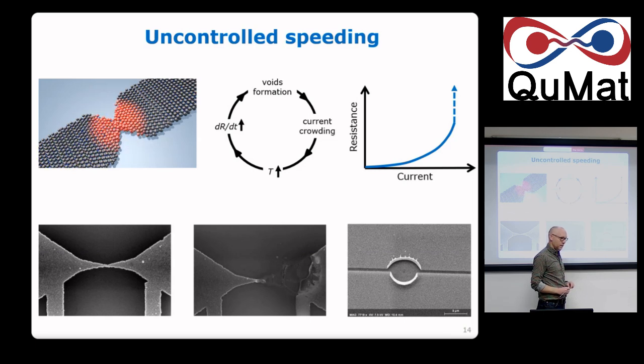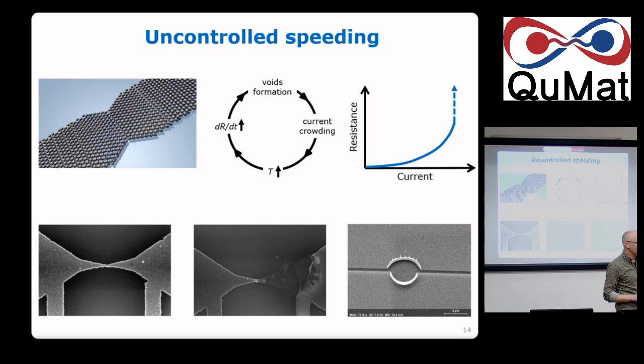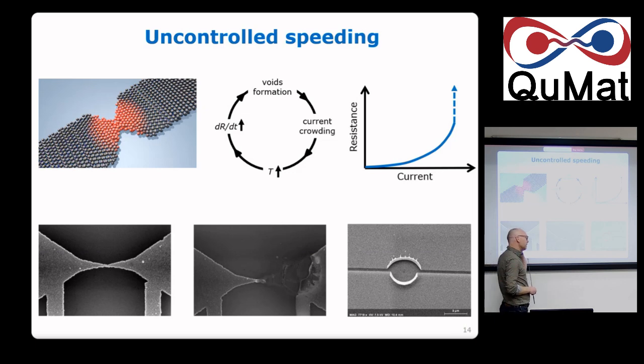Your initial slides had some comparison to the melting temperature, but it's the melting temperature of a bulk. This is of the bulk. No, not necessarily. Okay. Because here, in a nanoconstriction, I can imagine that the melting temperature would actually be much lower. And from the look of it, I don't know what the timescales are, but this could actually count as partial melting. You're totally right. Is there really a distinction between electromigration and melting? Yes, there is a clear one. You can see it. You can see the melting. It has a different shape, but still melting. I agree with you. It decreases, but it's not like it goes half. Not at the scale we are playing.